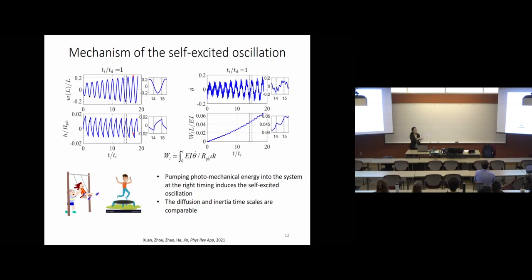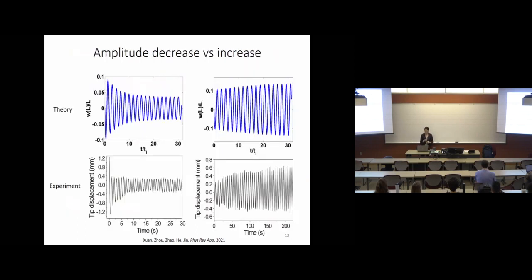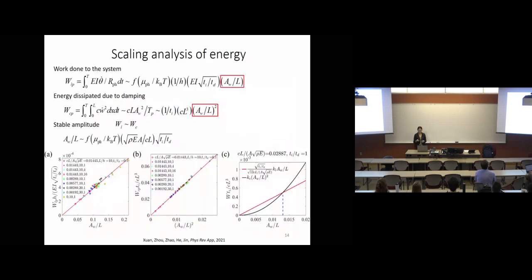So this is like when you push a swing or you jump on a trampoline, you need to do work at the right time. This is because the diffusion has some delay which creates this phase difference. Then moreover, we found that the time scales for the diffusion and inertia also have to be comparable, such that you can really pump energy into the system. So from our model, we can also tell the amplitude sometimes can increase, sometimes can decrease if you tune material property and tune geometry.